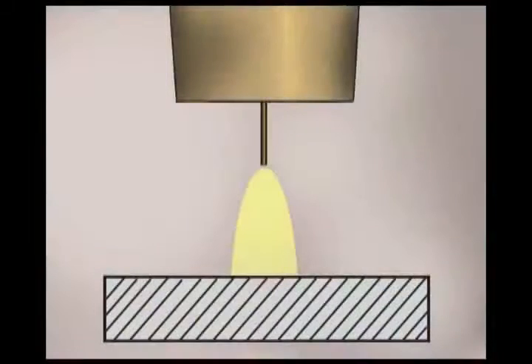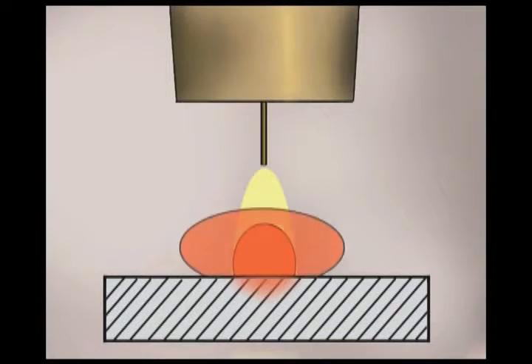To some extent, you can see this by watching the edge of the molten puddle. If the travel speed is too fast, the metal doesn't have time to heat up. The weld bead will just stack up on top and may not even fuse to the base metal. Traveling too slow will generally put the wire and the arc on the weld buildup, causing excessive filler metal deposit and reducing the amount of heat to the base metal.